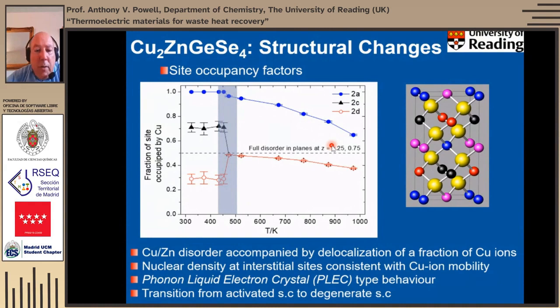And when we do a difference Fourier map, we see that that copper is actually distributed over a whole range of interstitial sites in this structure. So it looks as if that copper sublattice is starting to melt. So it looks like phonon-liquid electron crystal type behavior. And that's associated then with this change from an activated semiconductor to a degenerate semiconductor.